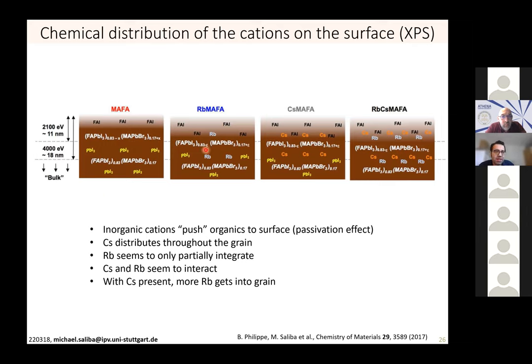it's distributed as well. This is an XPS study which we've conducted at the time. You see how the rubidium on its own doesn't penetrate very deeply into the grain, and then in the presence of cesium, it starts interacting. It seems more rubidium is going inside of the films as well, and this appears to have a passivation effect in the long run. So that's something resembling more CIGS, where alkali metal treatments are being used to passivate the crystal grains as well. But this is also an ongoing research topic at the moment.